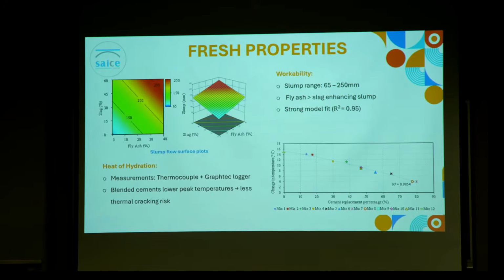which indicates higher workability. The heat of hydration trend indicated that blended cement significantly reduced peak temperatures during casting, which aids in preventing thermal cracking during mass concrete pours.